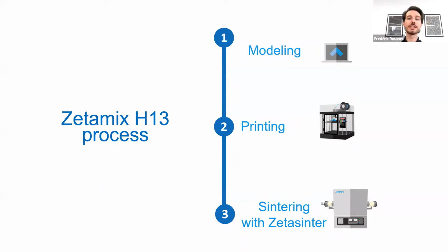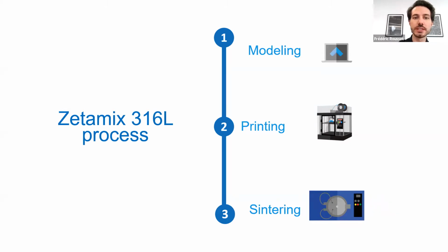Then for the H13 process, so the first metal that I'm going to present, you have all those steps, but you don't have any chemical debinding. The debinding will happen in the Zetamix while we are sintering, so at a lower temperature. But it removes a chemical debinding step, which is quite nice. And the last one is the 316L. It is the same as the H13, but you cannot sinter your pieces in the Zetamix. You have to use a furnace that is using hydrogen in it.